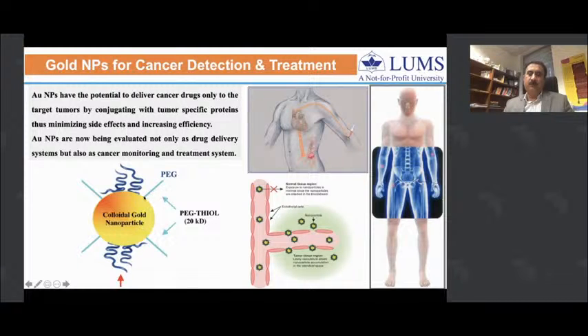For example, to avoid the immune system, what people do is usually coat them with hydrophilic ligands like polyethylene glycol, so that there is a water droplet around this as they are injected in the blood, and the immune system is unable to recognize that a foreign particle has been injected. So surface chemistry of these particles is really important if you want to use them for drug delivery applications.